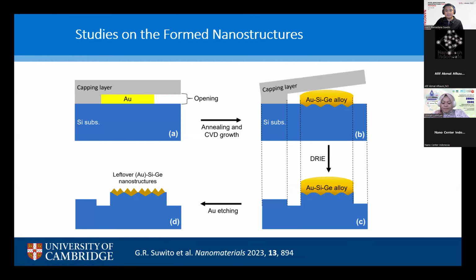For this reason, we prepared a sample by CVD at 375 degrees C with germane, lower than before, just a few SCCM, for an hour. Basically, we want to get a clear eutectic form before supersaturation, because after supersaturation you would get a larger germanium film, and then you would have difficulty studying the gold-germanium-silicon eutectic. So you need to do it before supersaturation in this case.